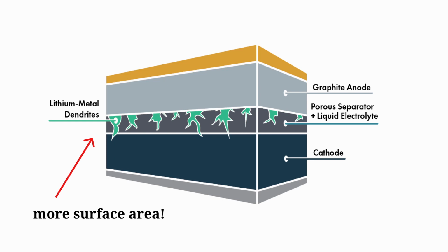The second thing that can cause corrosion to happen more often and faster is going to be over discharging. So the problem with over discharging is that it can lead to dendrite formation. We're going to dive deeper into this, but as it relates to corrosion, essentially what is happening is that there's fresh lithium metal exposed to the electrolyte. So the electrolyte is going to react and it's going to corrode that lithium metal.